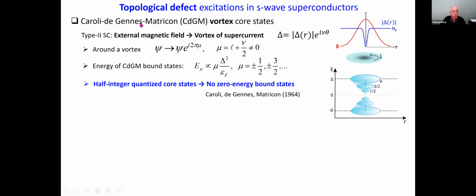Now, Caroli, de Gennes, and Matricon did the calculation and showed that these vortex core states are quantized, and they're quantized by half-odd integers. And it's very easy to understand this half-odd integer, because if you take a particle and go around the vortex, you pick up an angular momentum quantum number plus half of the vorticity. And that's why it's always half-odd integer. And in particular, it does not include the zero energy state.